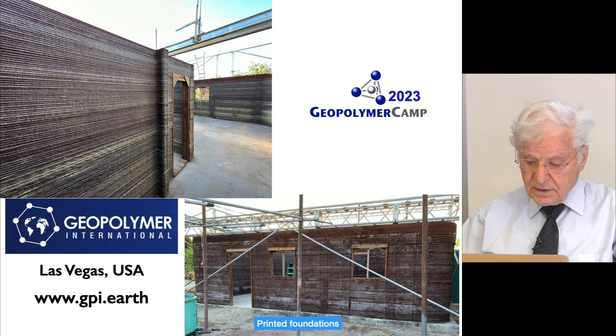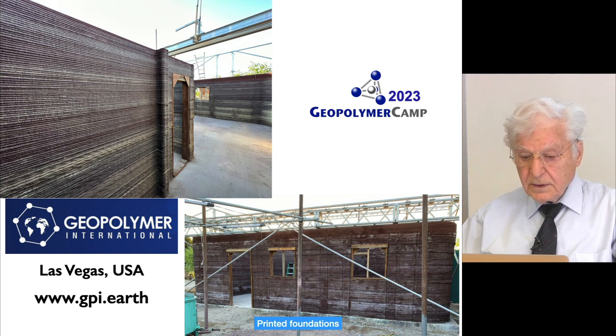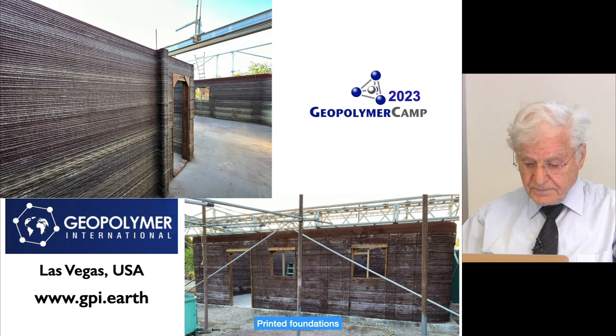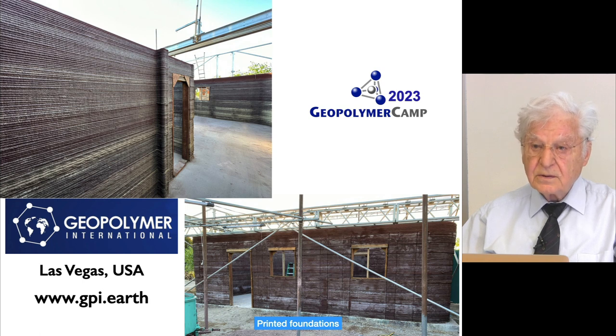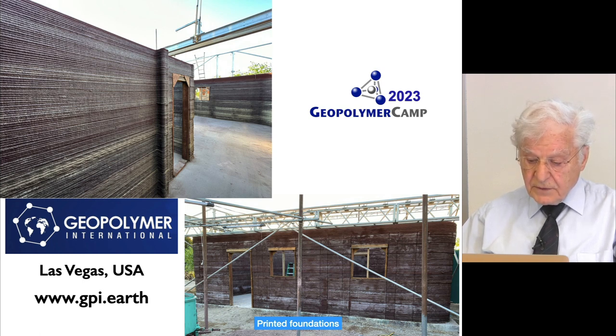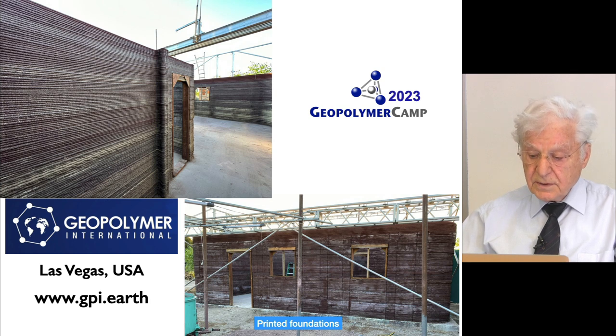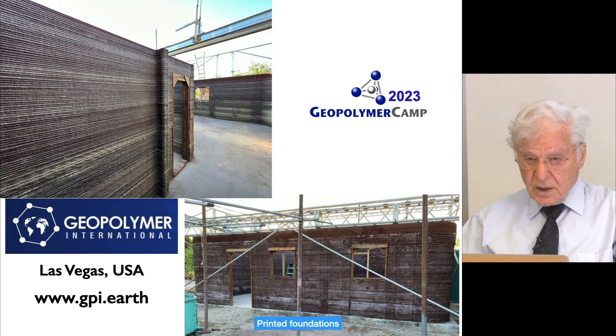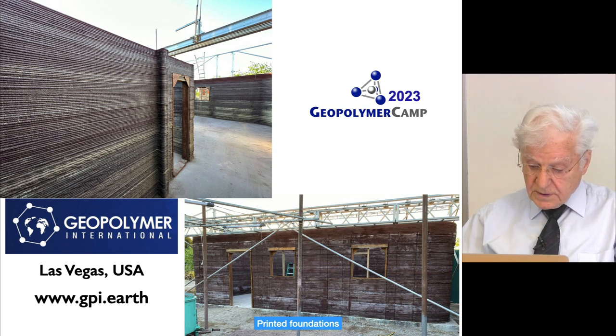It is an organic coating that they sprayed over the surface of the hardening geopolymer material in order to slow down the evaporation of water. It is critical to manage the evaporation of water during the curing process to prevent shrinkage and cracks. Additive manufacturing and 3D printing with the geopolymer technology is now the subject of numerous studies and trials, including those funded by major organizations such as the American Space Agency, NASA, the European Space Agency, ESA, and the Chinese government, for example.